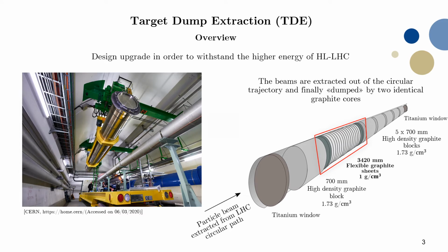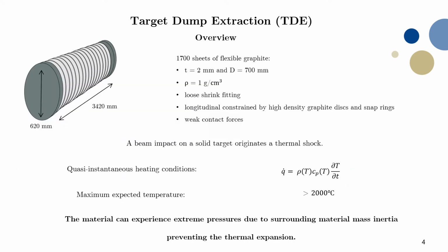At a certain point in the circular path, the beams are extracted in a tangential trajectory and finally dumped by two identical cores. These cores are made of several blocks of graphite with different densities, and the main focus of this project is especially on this part here, which is made of flexible graphite sheets. This core is made of 1,700 sheets of flexible graphite, each one with 2 millimeters of thickness and 1 gram per cubic centimeter of density. So the total length is more than 3 meters, and the diameter is roughly 62 centimeters.